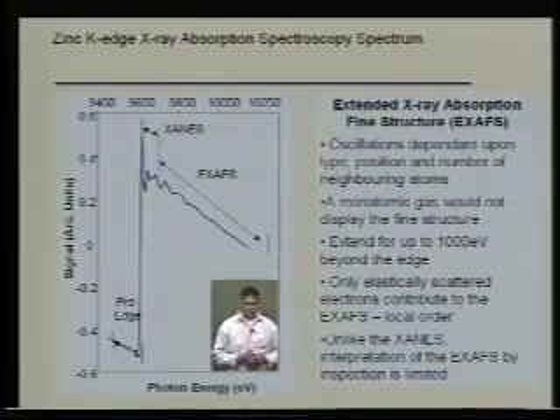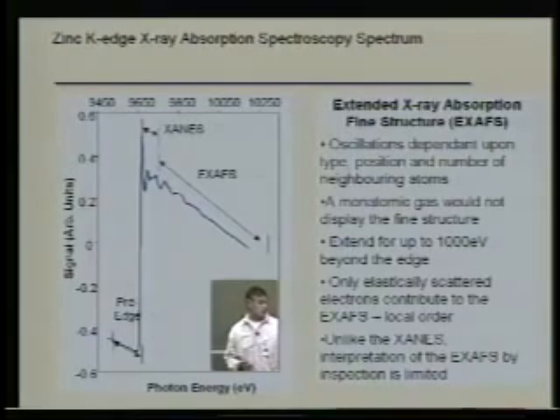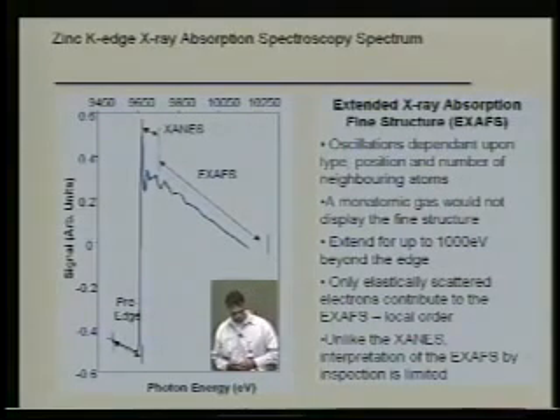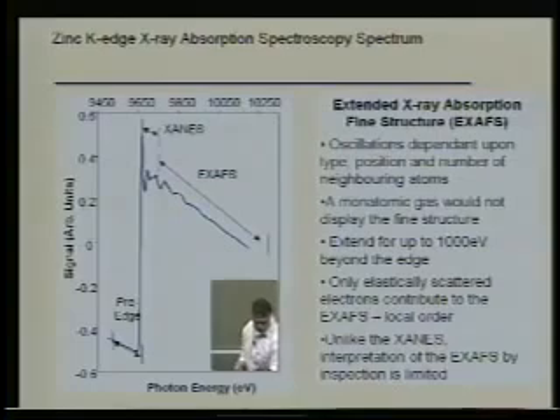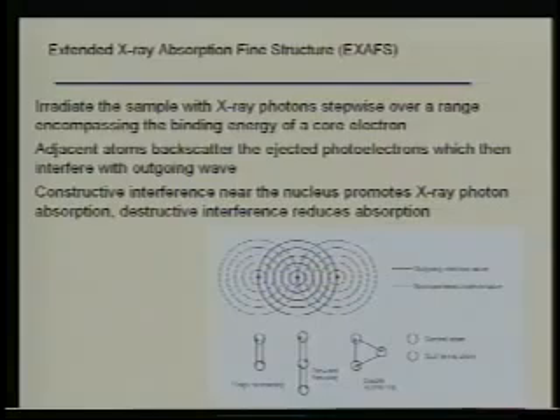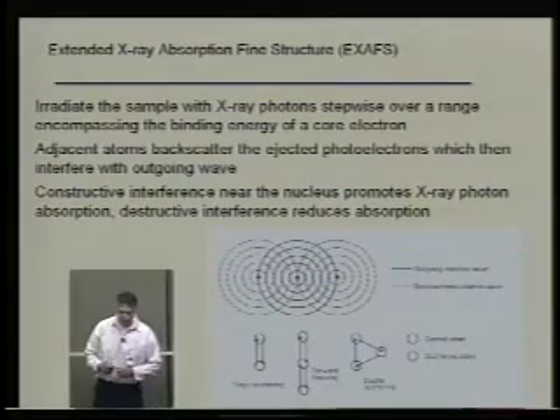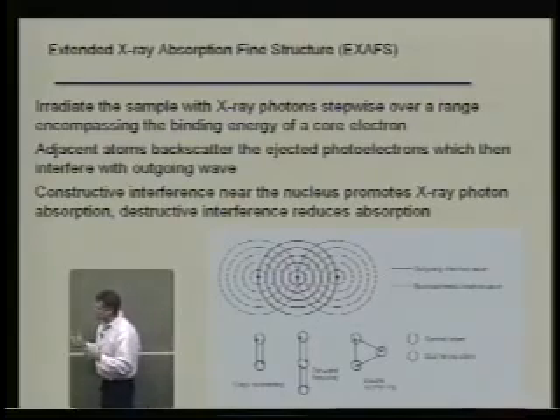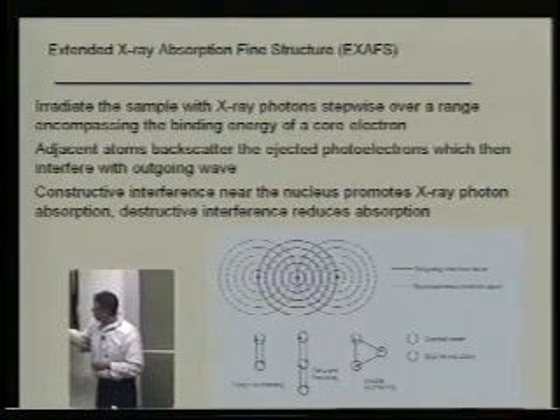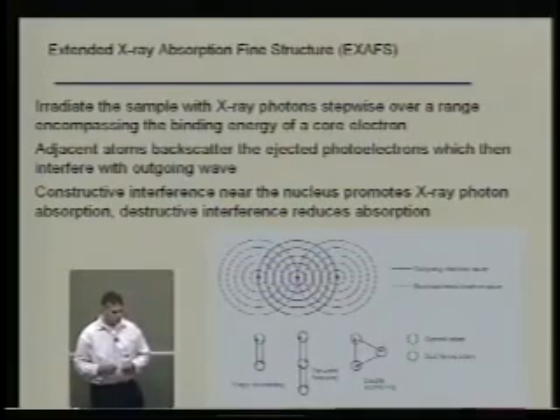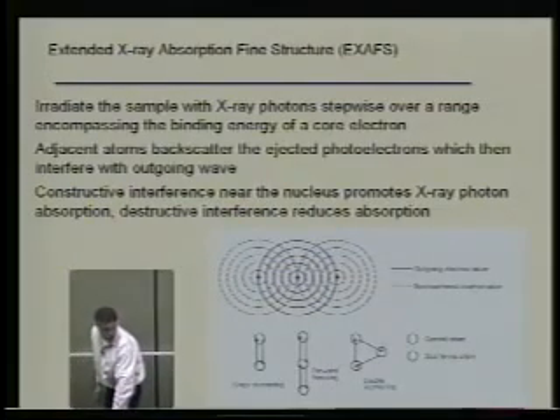Now, the thing about the XAFS is that just by looking at the data as it comes out, it's hard to interpret what's actually going on, whereas with the near edge, you can look at it and immediately get relevant materials science information. So what you would do to get information is, let's say you have your atom in the middle, and it's absorbed an X-ray, and you've ejected your photoelectrons. The photoelectrons disperse, and they can interact with the nearest neighbors. Interference is produced, and you get oscillations in your X-ray absorption structure.